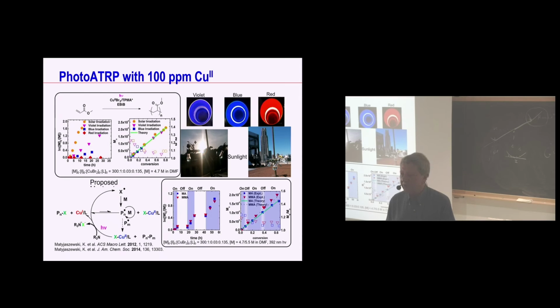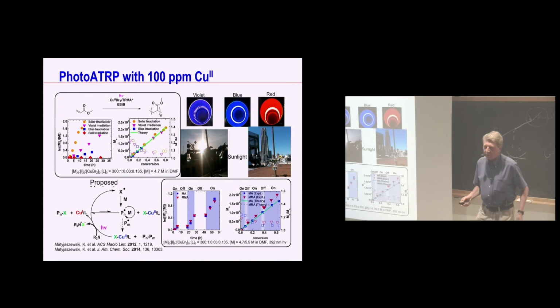In fact, some of these reducing agents consume oxygen as well. For many years, oxygen was the most powerful inhibitor of radical polymerization. You needed to bubble nitrogen or work under an inert atmosphere, in a glove box and so on. Now we can use light, and it works like a charm. So you can work in a completely open atmosphere.